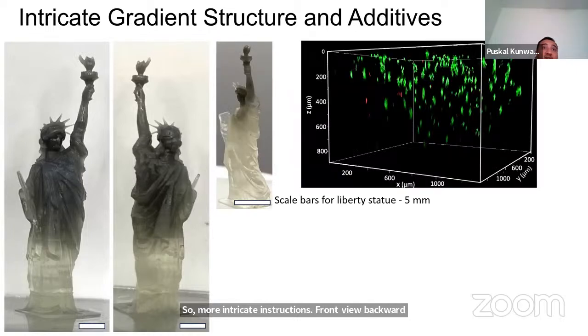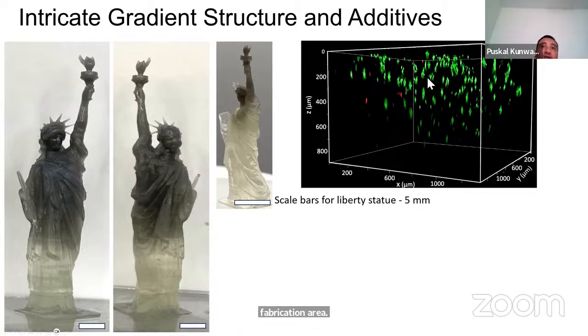We can also do a cell gradient, basically within your inline mixture, where you can add one cell solution and the other your bio ink, and the mixture mixes and brings it to the fabrication area. Then you can print, and this is a confocal image. Basically, green dots are live cells and red dots are dead cells. So you can see some sort of gradient formed within this printed construct.